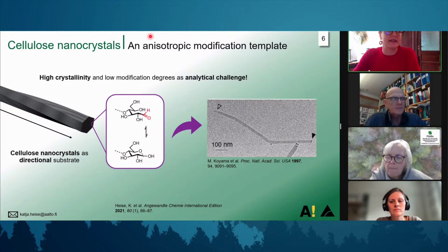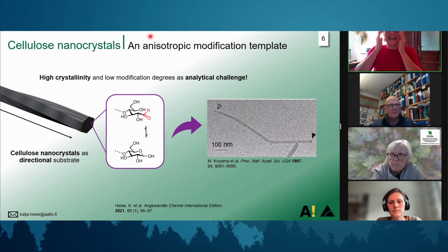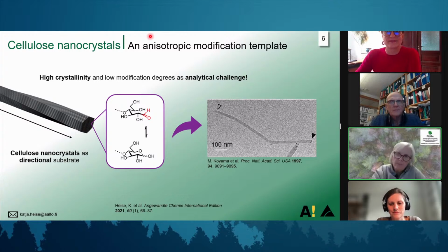But this also depends on the whole setup, because for some experiments we use really long pulse gradients, and this is more problematic combined with high temperatures for certain probes. It's something that an NMR expert, based on the instrument that is available, really has to check. I know that for certain instruments at Aalto, it's not really ideal. It depends on what they are defined for. And it's really for dissolving the samples properly, and also for transferring them, because if you transfer them after dissolution into the NMR tubes, you have really high viscosity. So it's actually quite challenging to handle the samples sometimes. Super, thank you. You're welcome.